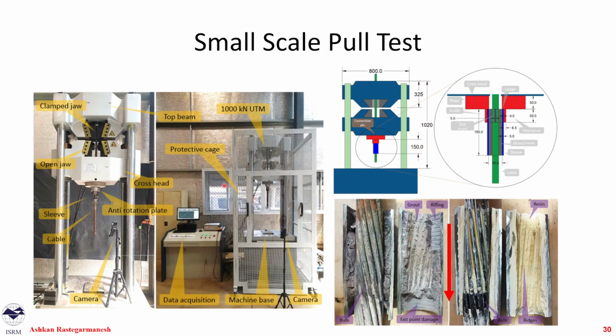This was the final test setup. So we had a different machine, much better. We had the anti-rotation section in the bottom. That's this section. You can see the details of it there. And the pull-out. And at the same time, because now we had access to the entry point of the cable, we were able to put the camera and study that. And on the right, you see the broken cables and how they look. The broken samples after the test.